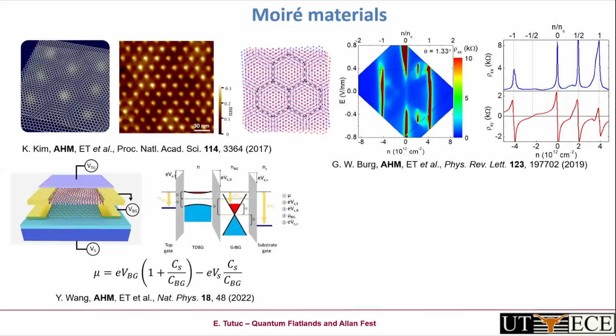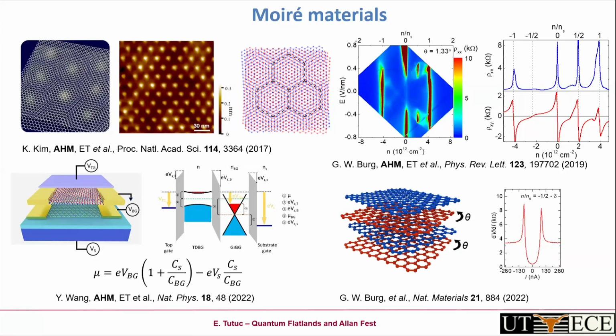We've actually complicated the sample structure where we take a moire material and we add a gate that we can probe resistively, and this can serve as a resistively detected Kelvin probe that allows us to measure the chemical potential of the electrons in the moire material. This is very useful to probe, for instance, topological properties.